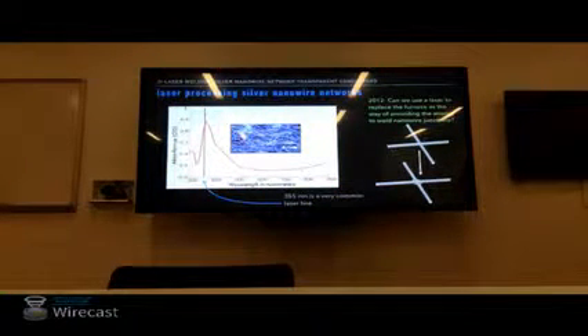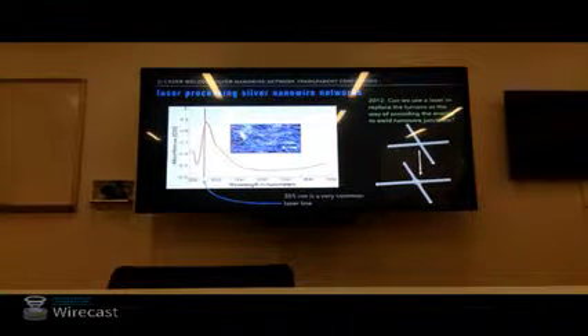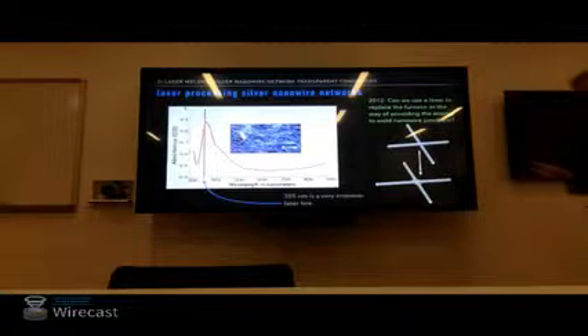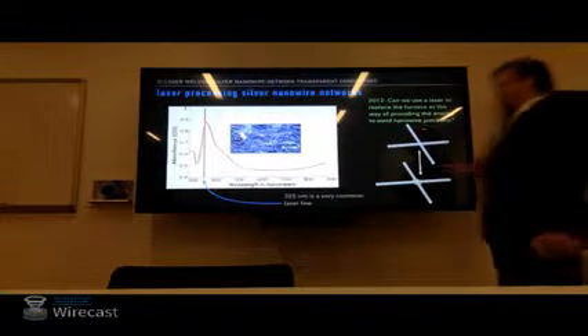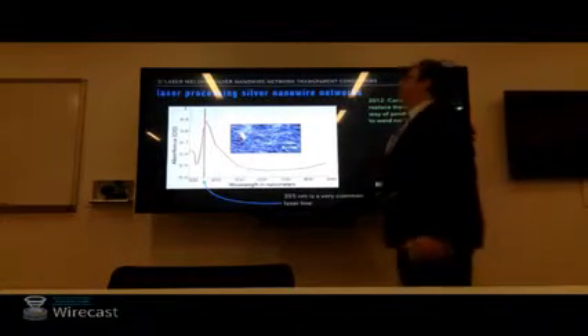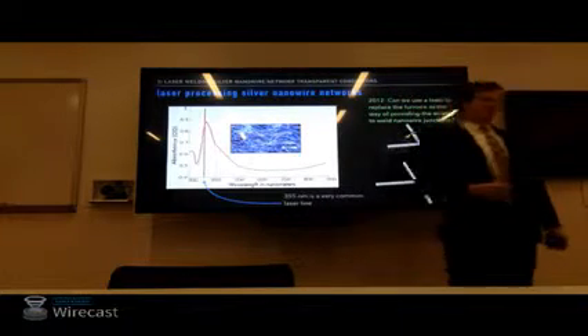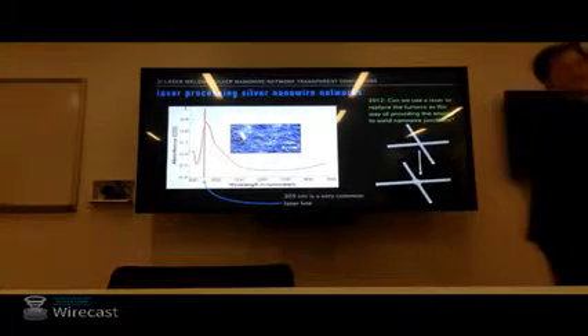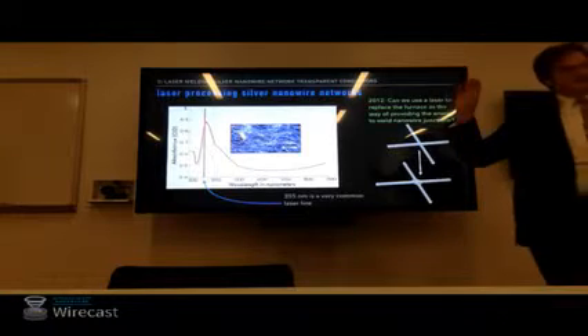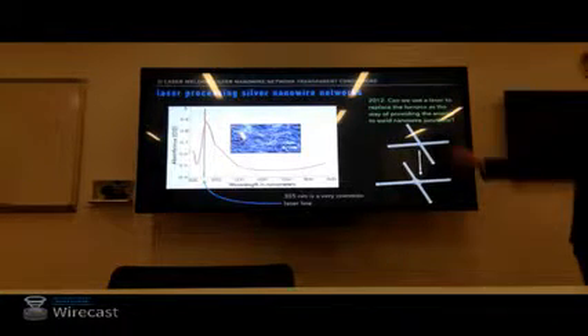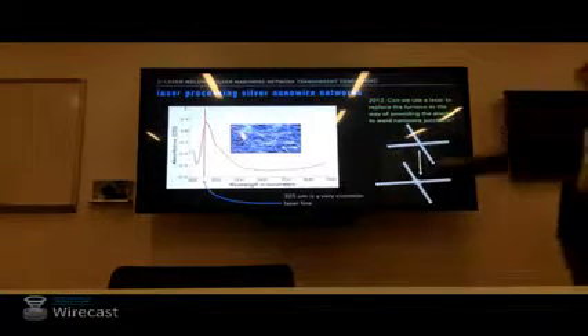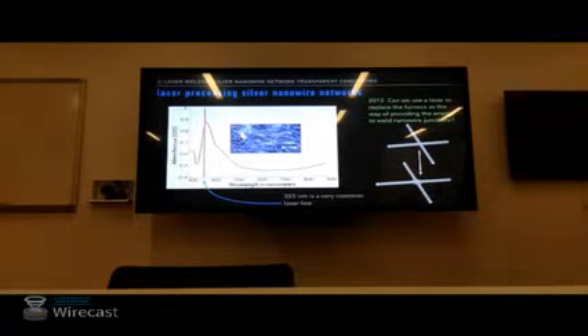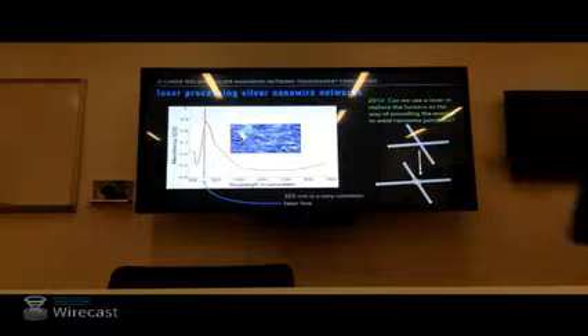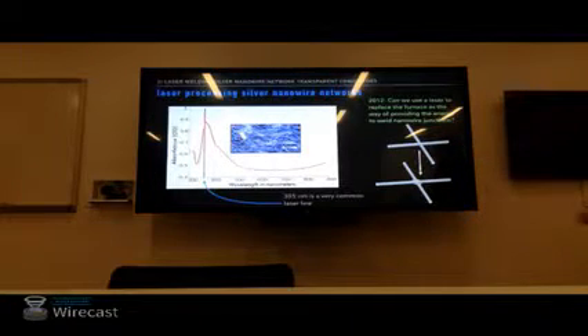We ask that because if you look at the absorptance spectrum of a dense silver nanowire network, now we use a very dense network here to pronounce features, but if you look at this absorbance spectrum, we see a nice absorptive resonance in the UV, right? It's outside of the visible. We want these things to be transparent to visible. But we see this nice resonance near a very common laser line. Now, in the Arnold lab, we've got at least 4 lasers that can access this line. So that's why this is exciting to us.